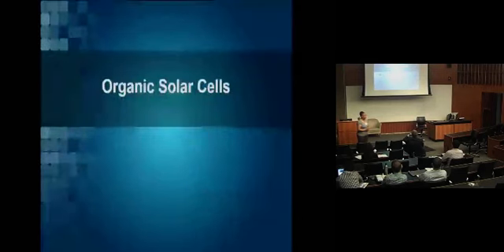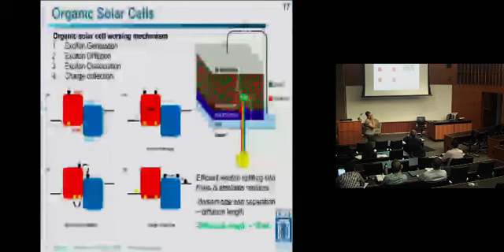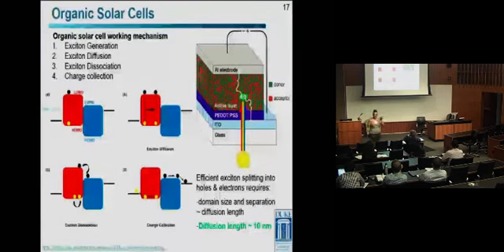So I want to spend some time talking about the work that we've done in organic solar cells. A lot of our work in this area has been to first understand where we are in terms of MAPLE deposition and what it gives us with the organic solar cells. Just as a quick review, for the organic solar cells, the working mechanism is basically you absorb light, you create an exciton. That exciton has to travel to the interface of two different materials, a donor and an acceptor material. At that interface, you can separate the exciton, and so then you can collect electrons and holes separately in the two different materials, the donor material and the acceptor material, for the charge collection.